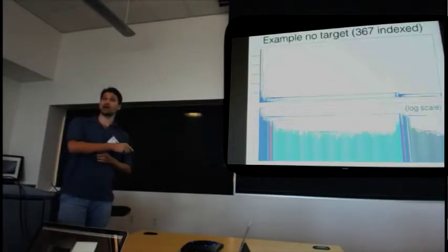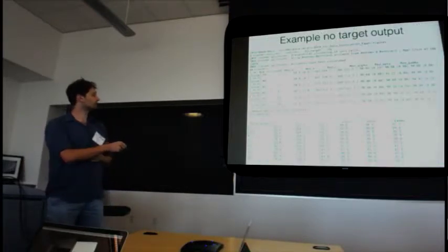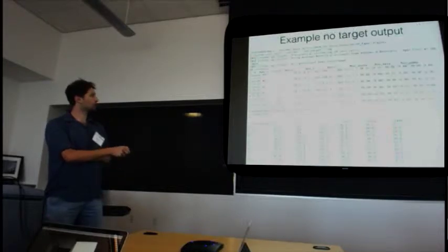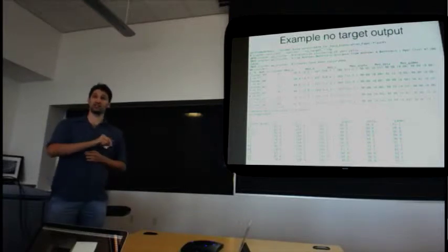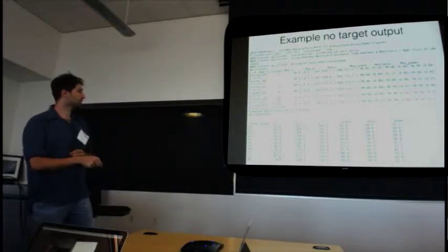So this does happen. If we look at the output from here, I just want to bring your attention to these two clusters: the short cell crystal form, that was the black one, and the long cell, the green one. In this case, you can see that if you actually swap b and c and then double the new c, you get the same thing. So it's roughly a doubling, but with a different symmetry, and actually in this case, a different unit cell contents. So it does matter.